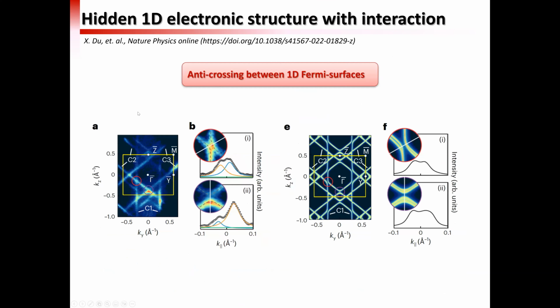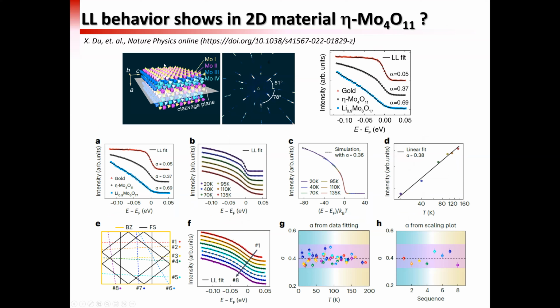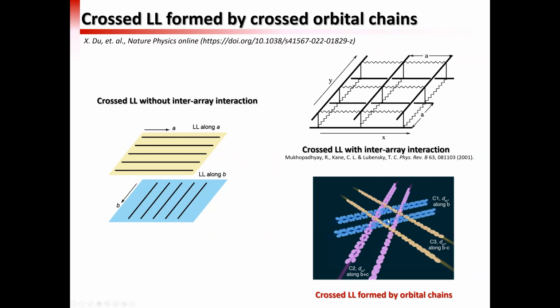It turns out, you can see from the Fermi surface map that there are three groups of parallel lines representing the three chain directions, and in between these linear Fermi surfaces there is anti-crossing behavior showing that there are 1D chains and they have interaction. So how can we find this 1D chain in this apparently two-dimensional material? It turns out that it is the different orbitals of the atoms that give us this hidden 1D chain.